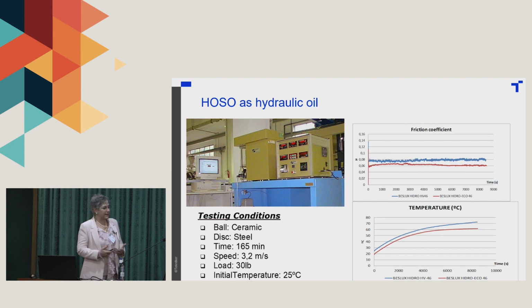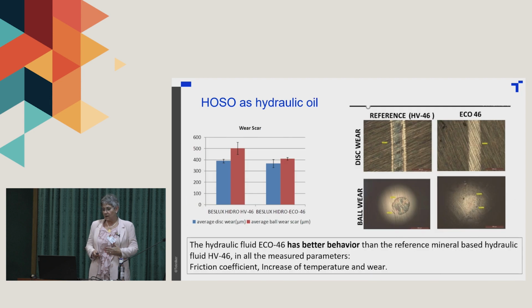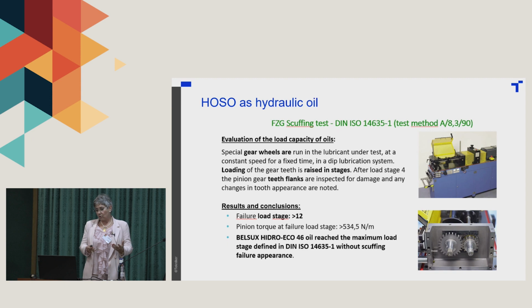And how do we measure at the laboratory scale the properties of the lubricant comparing with mineral oil, for example. Then if we measure the friction and temperature, it's possible to see that the friction coefficient is lower and also the temperature is lower. This causes less friction and less increase of temperature. And also we can see that the wear properties are good, with less wear damage in the biolubricants comparing with a mineral oil, and also the FZG test, that is the test in gears, shows that it is possible to reach a failure load at the stage of 12. That means that they have good properties from the point of view of gears.